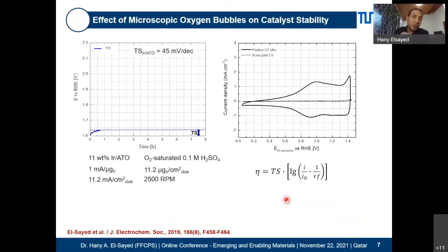In order to show that what is in the literature is not really very accurate, we did the following. We did the typical experiment that is usually done there, which is applying a constant current and seeing how the potential increases with time.